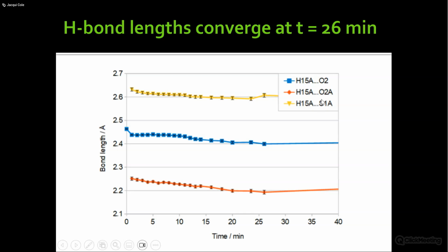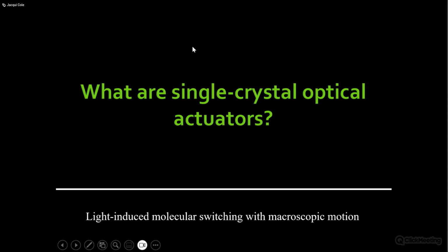So in that reaction cavity, it seems that at 26 minutes, these interactions with hydrogen, non-bonded interactions essentially, decrease as you would expect as a function of time, and then suddenly they flatline. It's like they can't change anymore. They're somehow locked in some way, and these are very subtle changes, but they're very consistent. I've done the experiment again, and essentially you get the same manifestation. So I hope that's helpful.